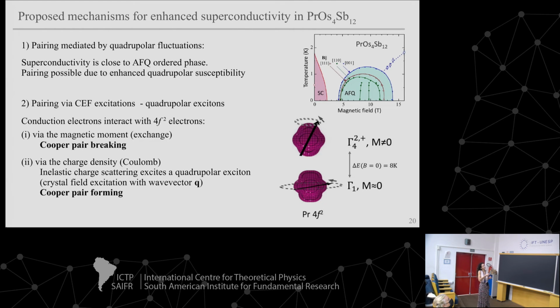And there are two scattering mechanisms going on in this case. One is the exchange scattering, which would be Cooper pair breaking, and we know that that's present in the system and that actually we're enhancing it as we increase the field. And then there would be an inelastic charge scattering, also known as aspherical Coulomb scattering. This would scatter off the quadrupolar exciton, and this would be Cooper pair forming. Now, this is usually rather weak, but it can dominate if the exchange scattering is also weak.